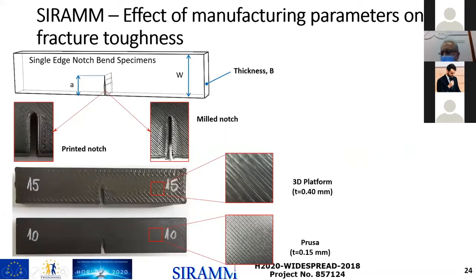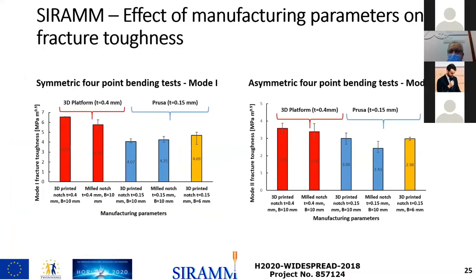We also want to see what happens if we manufacture the notch or we cut the notch by milling. So, the results are here also for the two printers. The highest fracture toughness value was 6.5 megapascal square root meter, obtained from the 3D platform with a layer thickness of 0.4, and lower values were obtained on the Prusa printer, around 4 megapascal square root meter. Also for mode 2, the values are lower, around 3.58 is the highest mode 2 fracture toughness, obtained also from the 3D platform printer. And all the fracture toughness values with directly 3D printed notch have higher values compared with those where the notches were manufactured.